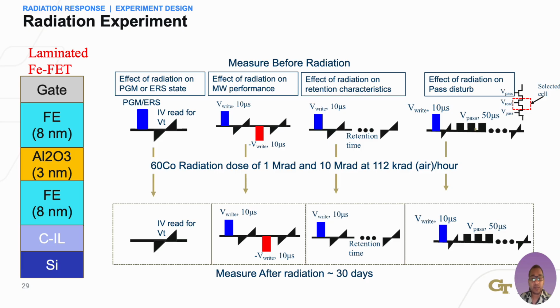We examine the stored state stability, memory window, incremental programming and erasing, retention and disturb. These are discrete device total ionizing dose experiments. They test whether the polarization based cell itself retains useful behavior under extreme accumulated dose. The very high doses are intentional. They expose weak mechanisms and create margin relative to many mission requirements.